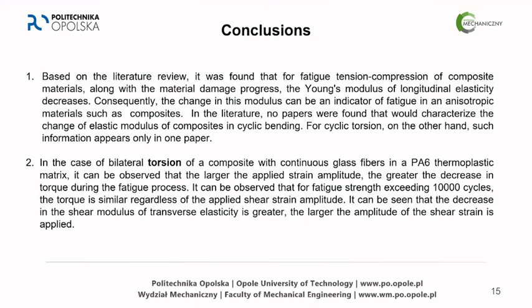Getting to the conclusions, we can see that first of all, based on the literature review, there are several propositions for fatigue, tension, compression of composite materials, how to use this, how the Young modulus changes. However, for bending, there were no propositions found, and for torsion, there was just one, so well, it's not much yet, actually. The second conclusion is that when we talk about torsion, in this case, it's worth saying which material it was. It was PA6 thermoplastic matrix with continuous glass fibers, but we hope that this way of thinking would be also true for other materials.